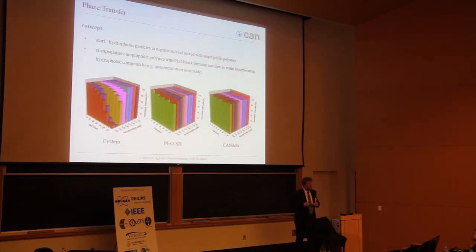Just to finish with, I think it's very important to talk a little bit about the phase transfer, because up until now we have only seen particles which are soluble in organics. But if we want to do some life science application, of course, we need the particles in water. So what we do is we start with our hydrophobic particles, and then we mix them with an amphiphilic polymer, add some water, and due to the addition of the water, the polymer forms micelles, and the micelles encapsulate the hydrophobic particles. And to check if this works really well, quantum dots are usually a good choice.